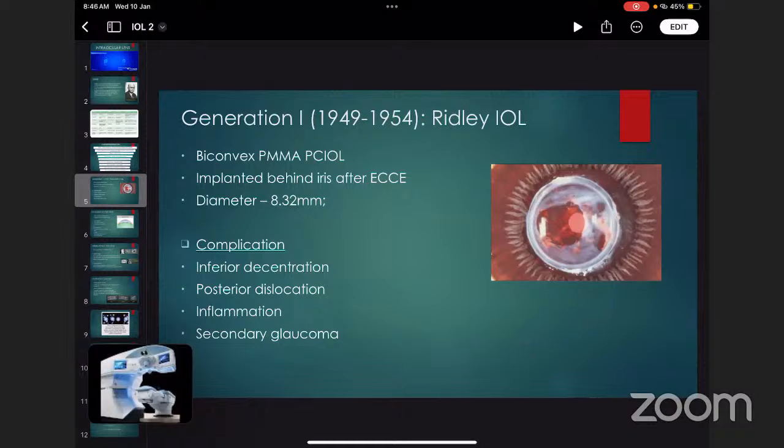Generation 1, from 1949 to 1954, was Ridley IOL, biconvex PMMA-PC IOL implanted behind the iris after extracapsular cataract extraction. It was without haptics, with diameter of 8.32 mm. But complications included inferior decentration, posterior dislocation, inflammation, and secondary glaucoma.